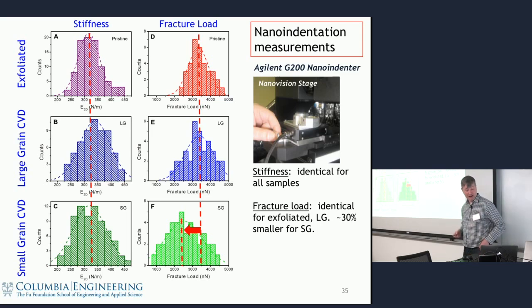And what we found was that if we looked at, again, stiffness and fracture load of exfoliated material, we saw that if we used large grain CVD grown graphene, so that there shouldn't be any grain boundaries inside the membrane, we saw virtually no difference in either the stiffness or the fracture load. So CVD doesn't seem to be worse from a mechanical point of view. On the other hand, when we looked at small grain CVD, we saw the same stiffness. That's a good check, because small defects shouldn't change the intrinsic stiffness of the material. But we saw a noticeable reduction in the fracture load, as one would expect. But it was a lot less than was seen before. So we're still in the range of thousands of nanonewtons rather than tens to hundreds.